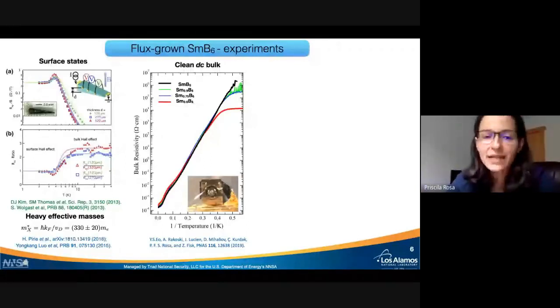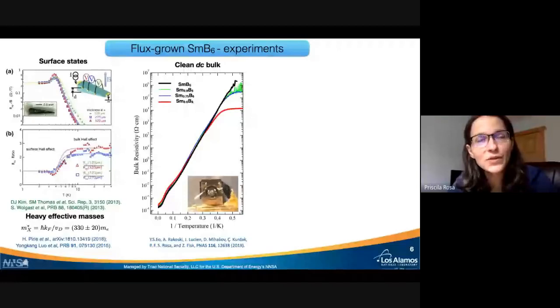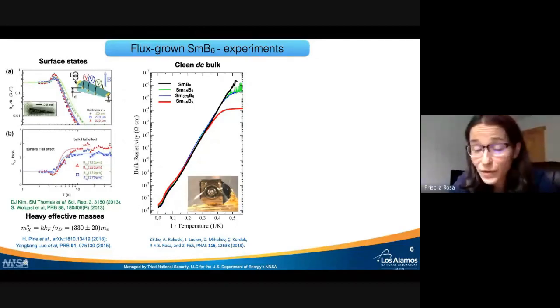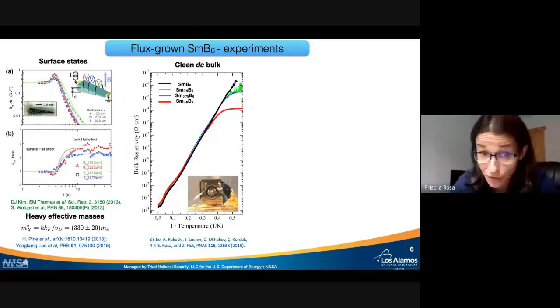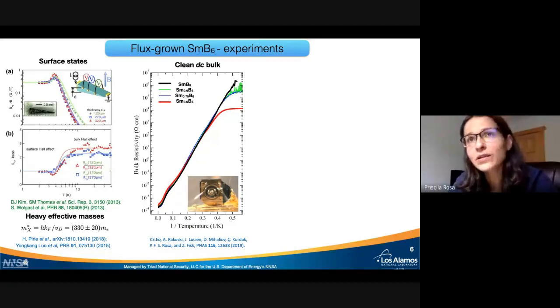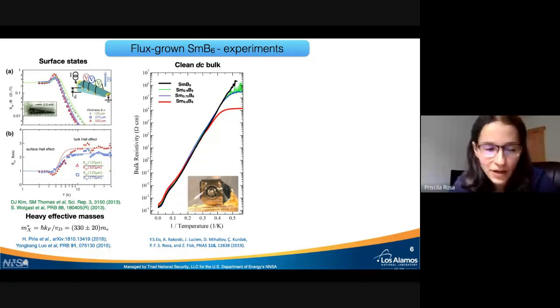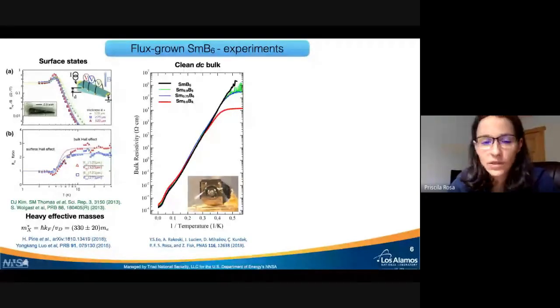There has been a lot of debate on these materials concerning quantum oscillations. So quantum oscillations are a result of the application of a magnetic field in general in a very clean material. And this is a clean material and a metallic material. In this case, we have an insulator. So when people discovered or reported quantum oscillations in this material, there was a lot of controversy and discussion, let's say, because one would ask, how is that possible, right? So many theories resulted from that.